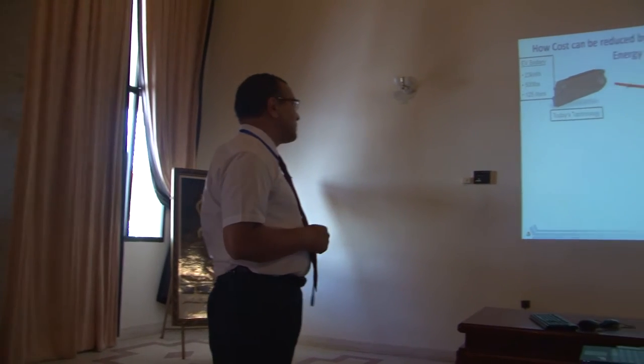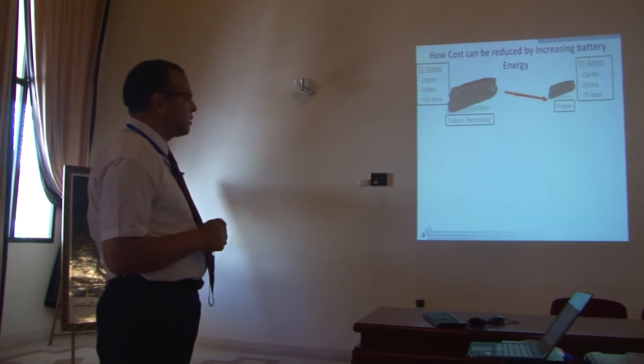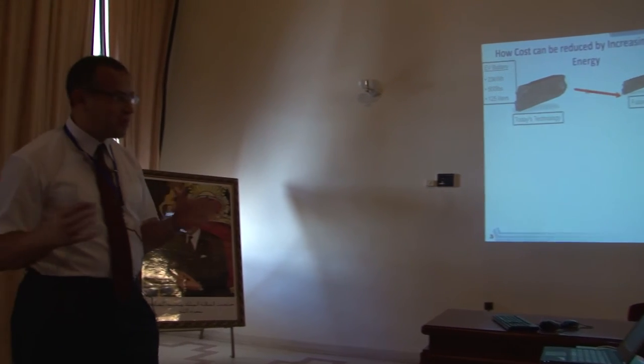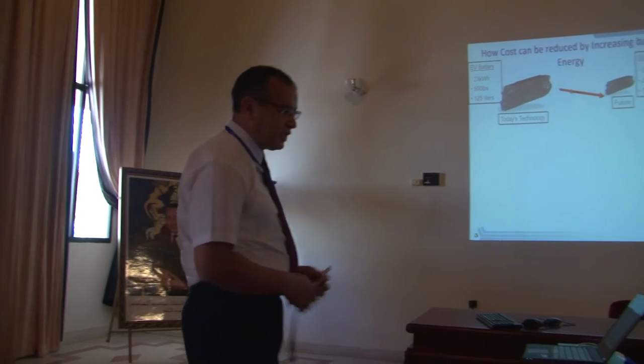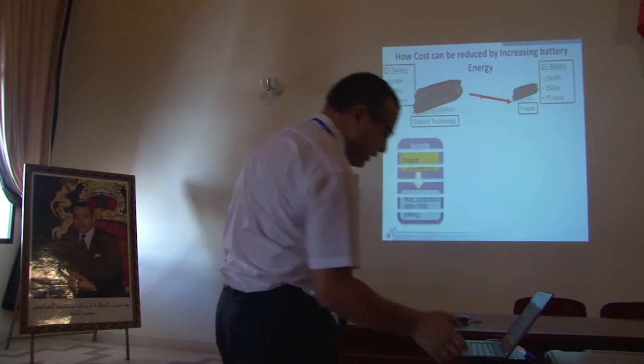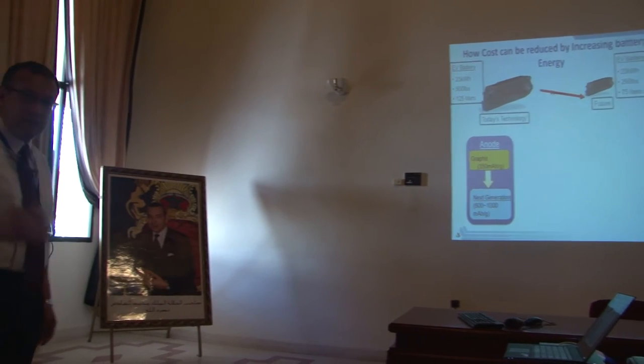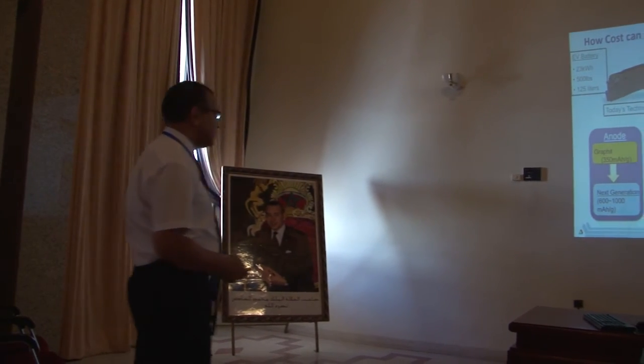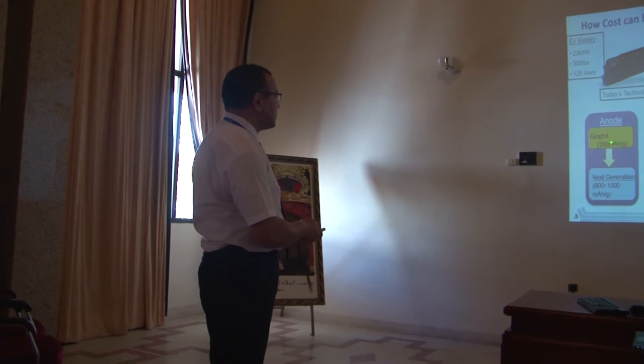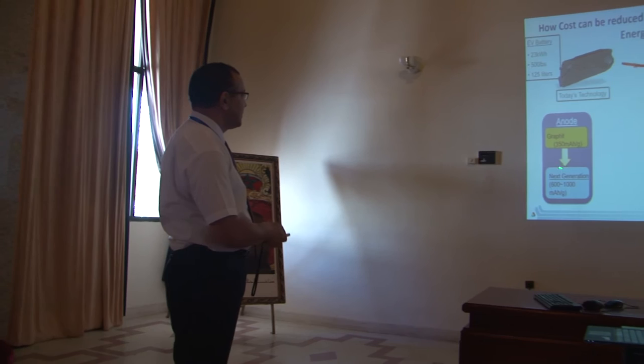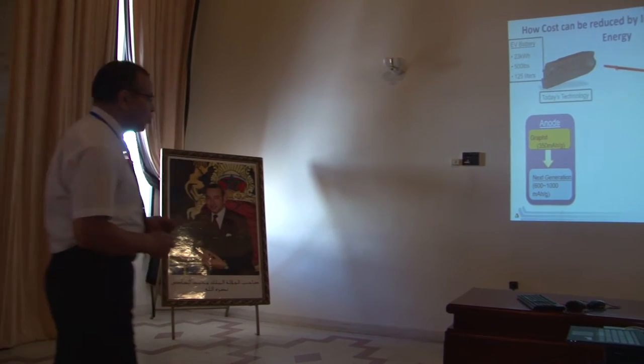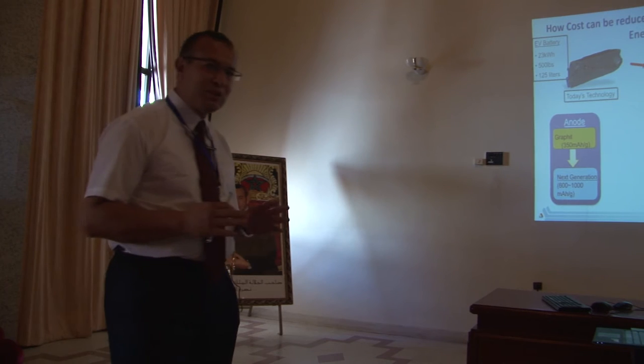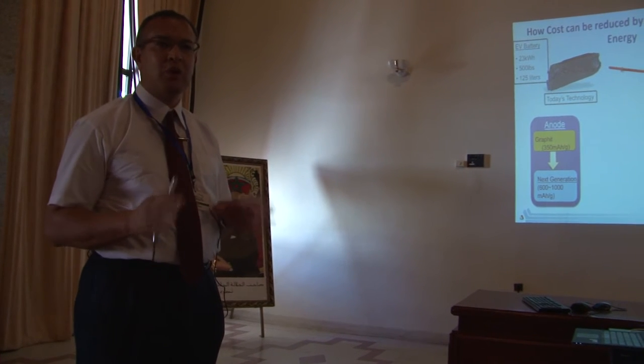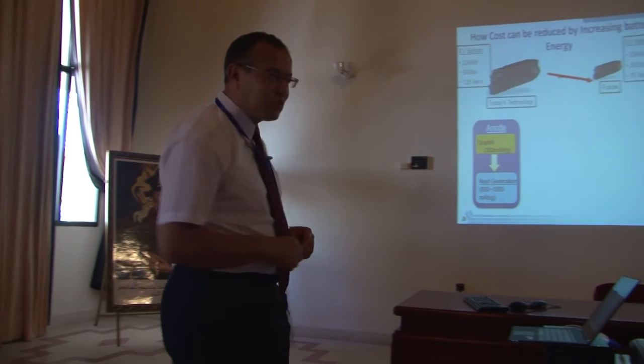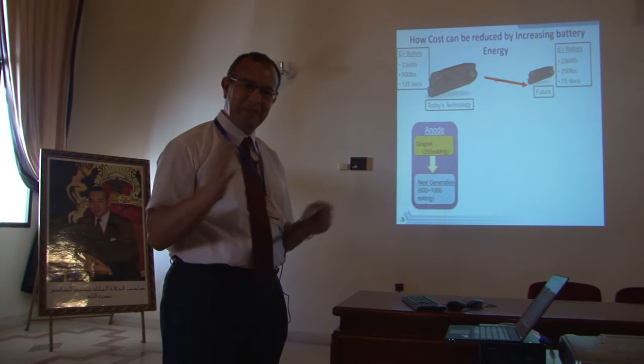Because a lot of people change the cathode from cobalt base to manganese base, the impact of that change at the cathode level is only 8%. So your margin is very small. This is a way to increase the energy. And how can you do that? You can increase the energy by increasing the anode capacity. We heard the speaker talk about some interesting work on silicon. At the moment we are at graphite, at 350 milliampere hours per gram. We are mostly looking at 600 to 1,000. Very practical, because there is no anode that can match 2,000 or 3,000 milliampere hours per gram. Sorry about that, but that's the reality.